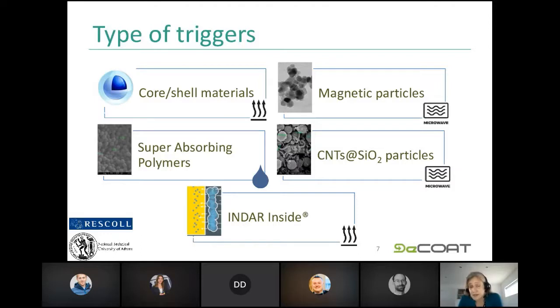We can also add magnetic particles or carbon nanotubes, which are adsorbed on silica, into the coating. And these materials can be triggered by a microwave. They will heat up, and via the heating this will reduce the strength of the coating, and then we can remove it. And a fifth principle is the INDAR technology of Rescoll, and what they're doing is, upon temperature increase, the additives will decompose and form a gas, and this gas will trigger the debonding.